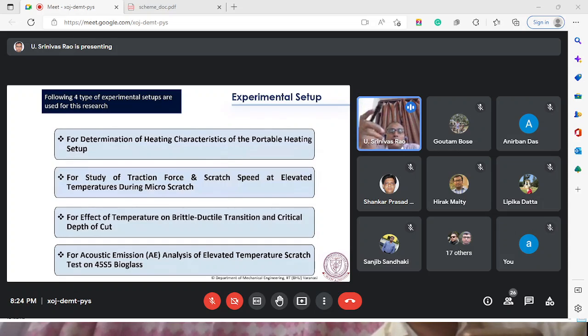As I told, the bulk heating and then doing some experiments to obtain the critical depth. A portable heating setup has been developed. Then that heating setup is loaded to a scratch tester on which the specimen is mounted. Then the effect of the traction force and scratch speed at different temperatures are checked. And from there we found the brittle ductile transition and critical depth of cut. Further, we have done optimization of that. So I will give some idea about these things.